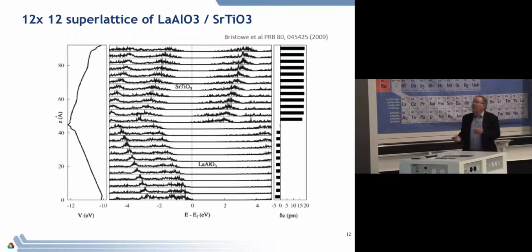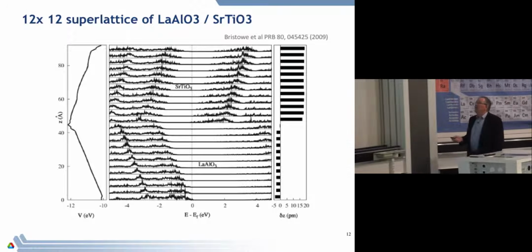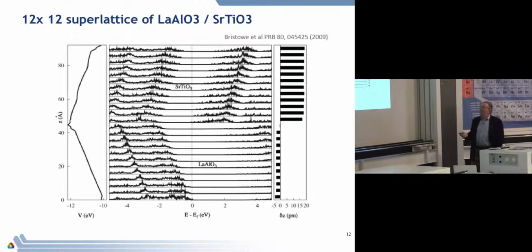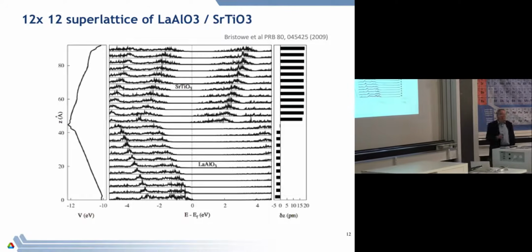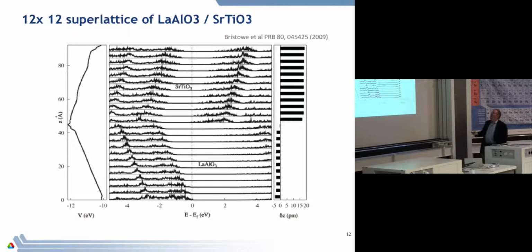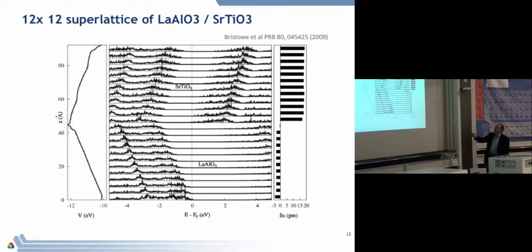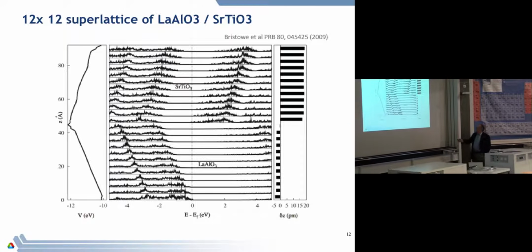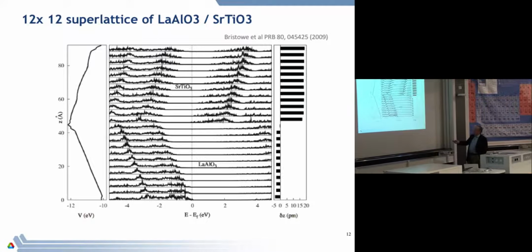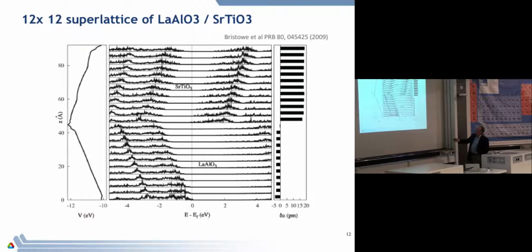Now, by the way, just to prove that it really does work, this is what the band structure calculation looks like if you do it for something like that. Here's lanthanum aluminate, here's the strontium titanate. Lanthanum aluminate is a wide band gap semiconductor. This is going up in the Z direction. So as you see that, we've got 12 layers of these, and you can see basically that the potential just moves down. This is the potential of the band gap. And here it comes back up the other way.